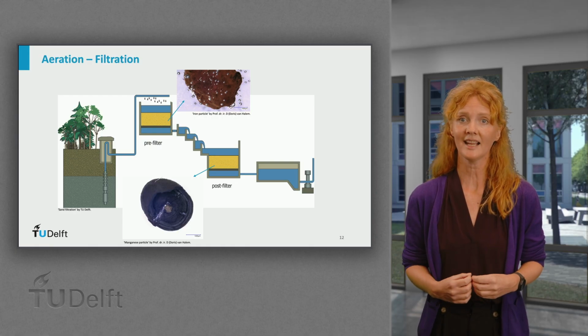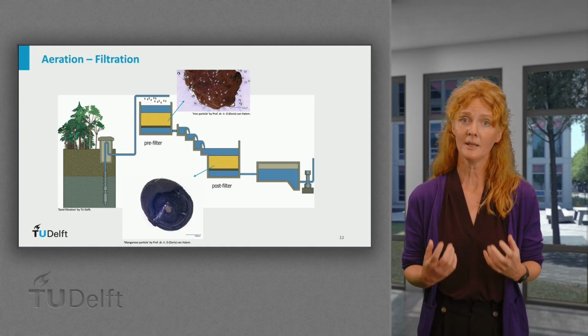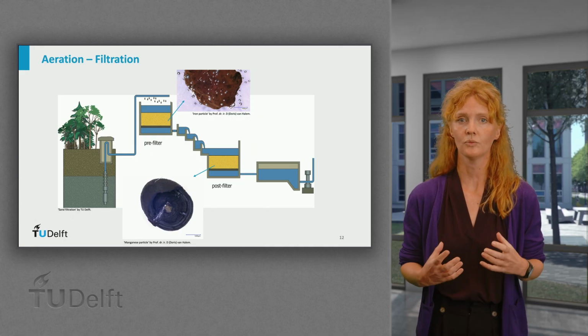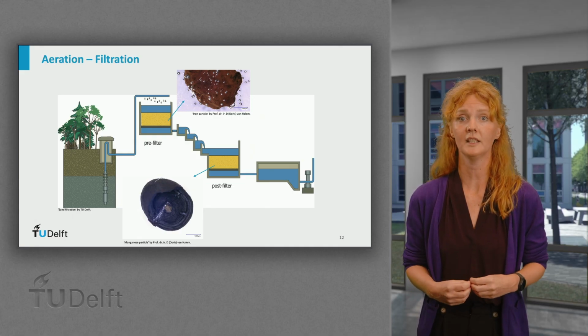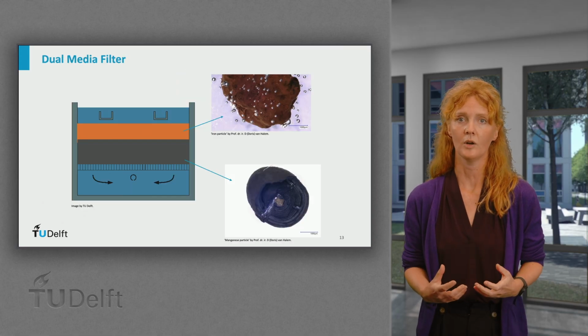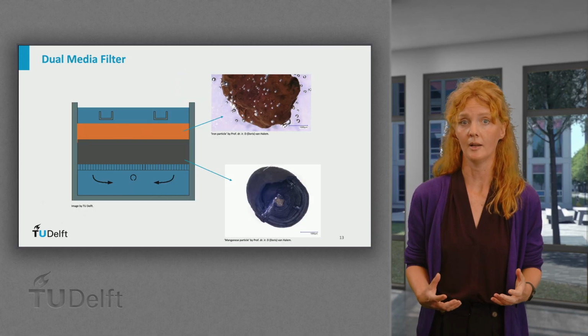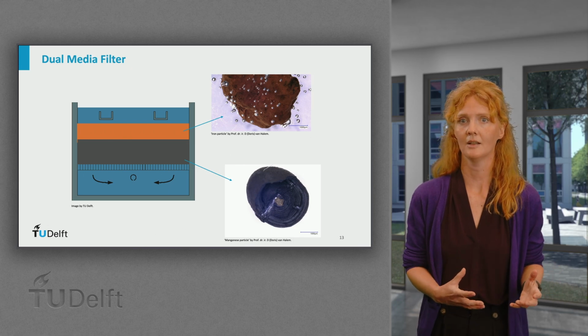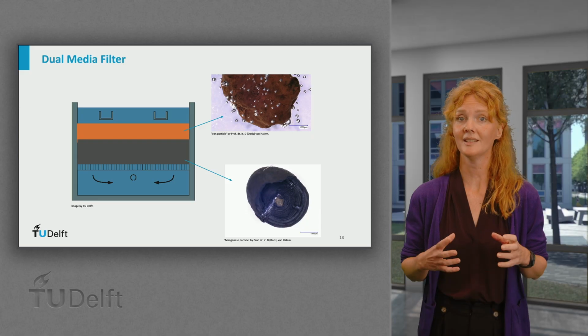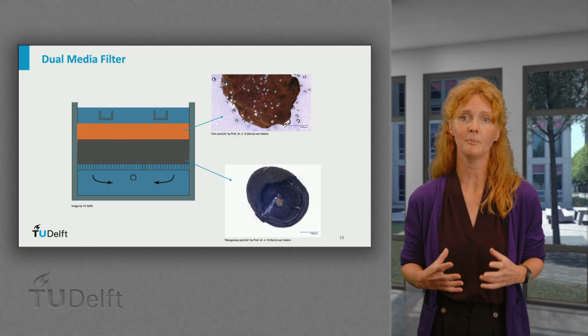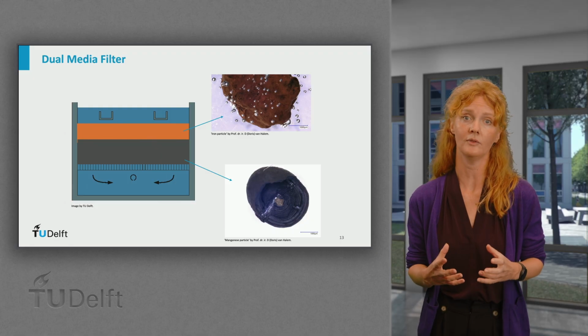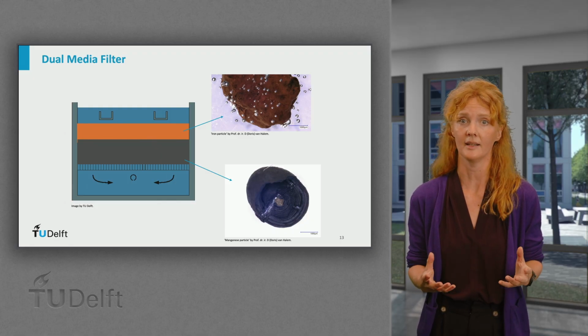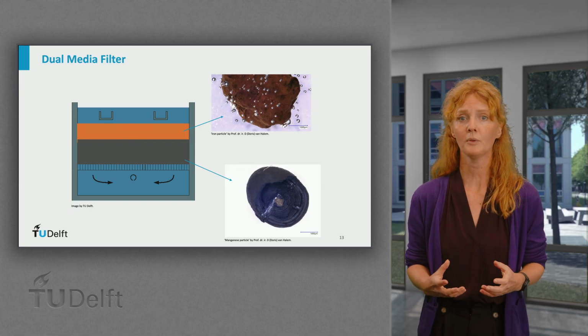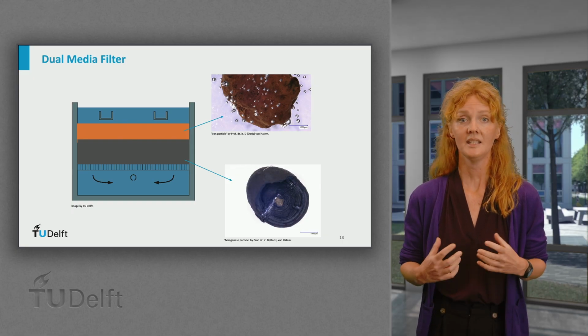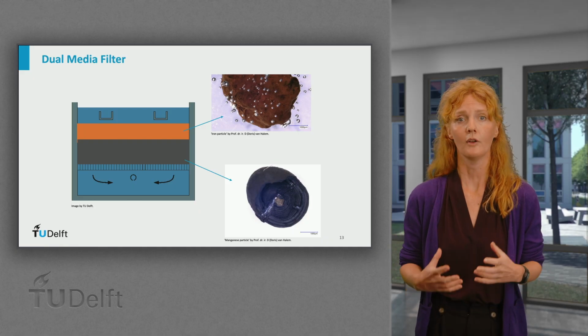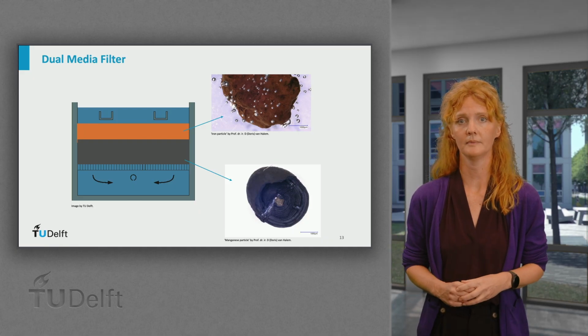With two filters, a second aeration step can be added as well, which might be needed to supply sufficient oxygen and to reach sufficiently high pH for manganese removal in the post-filter. In groundwaters with relatively low concentrations of iron and ammonium, and thus lower oxygen demand, one could also design two compartments within the same filter. This can be done by applying a dual media bed, with a top layer of lighter material, like pumice or anthracite. The difference in density will prevent the sand and the top layer to mix, maintaining two distinct compartments for iron removal in the top and manganese in the bottom.